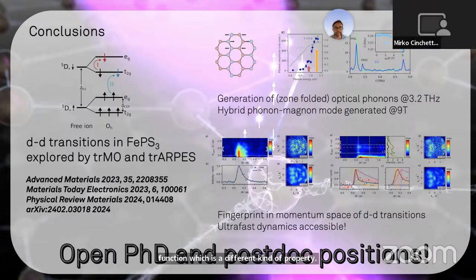Yes, but in principle, if you do a 2-photon photoemission experiment, you measure lifetime. When you measure a lifetime, of course, you have different parts of the lifetime. You have the one due to electron-electron scattering, for example, but then you also have electron-phonon, electron-magnon, and so on. And the question is, what do you see then in the photoemission? This depends also on the energy resolution of your experiments. So what I was mentioning is that one possibility why we see in the ARPES experiments a longer lifetime than in the line width would be that in the ARPES we don't see some relaxation channels.